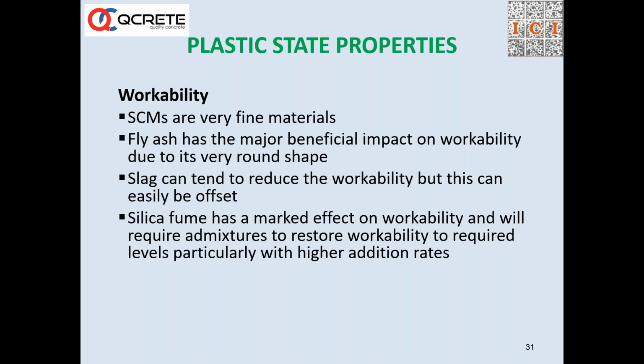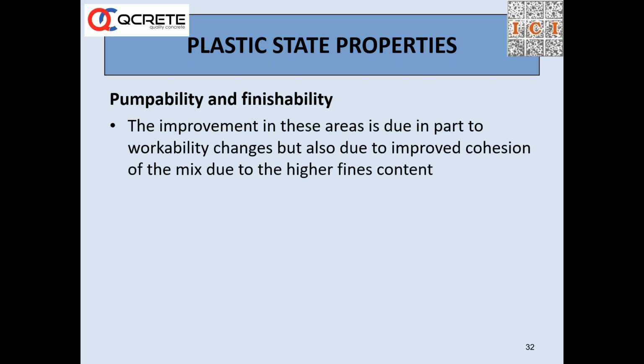Silica fume in this direction, silica fume is a killer of slump. It means it reduces the slump, but of course you can compensate for that with usage of better admixture or a higher dosage of admixture. Pumpability and finishability are definitely better, and hence it goes without saying that the cover concrete becomes denser if the finish is good, and hence the chlorides and sulfates cannot easily penetrate. If the finish has a lot of blemishes like crevices and all, the chlorides and sulfates can enter. So the concrete cover becomes denser, better.